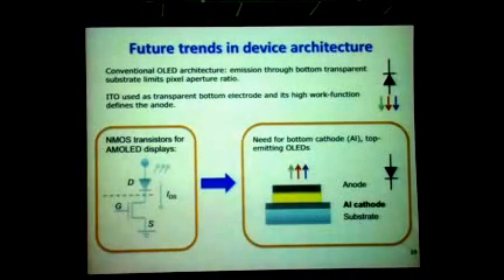A lot of these early devices are built in a geometry where you start with a transparent substrate, which is ITO-coated glass, and ITO is used as the anode. Then you have emission through the bottom of the substrate. Now that has multiple problems. One is that because you're emitting through the substrate, and because in an active matrix display you always have some electronics to drive the pixel, you're actually limited in the pixel aperture ratio.